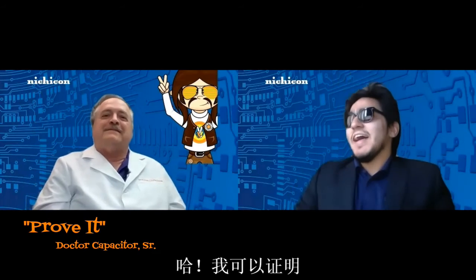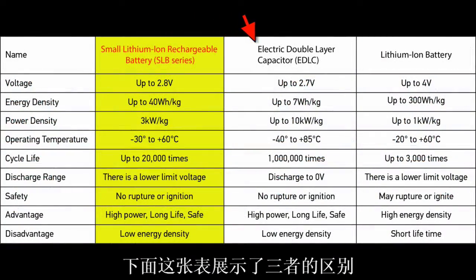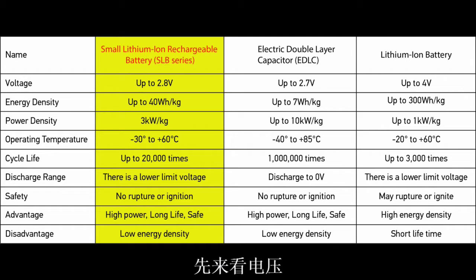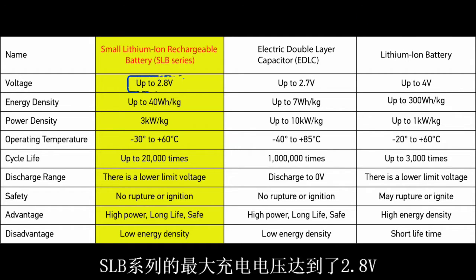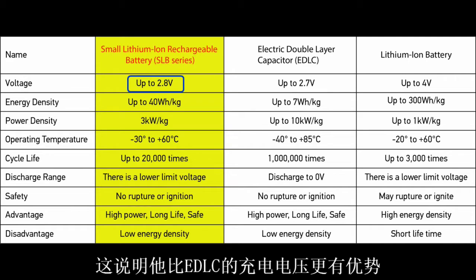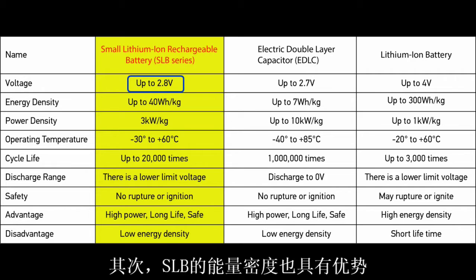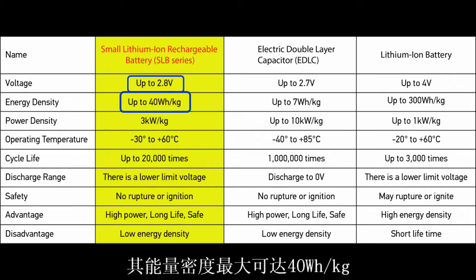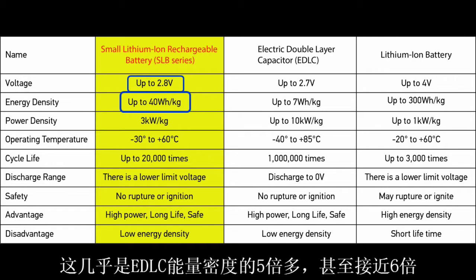Ha! I came prepared for that. This chart shows a column for the SLB and EDLC and a lithium ion battery. First, look at the voltage. The SLB goes up to 2.8 volts, which gives it an advantage over the EDLC. Second, look at the energy density. With up to 40 watt hours per kilogram, it exceeds the EDLC by 5 times, almost 6.